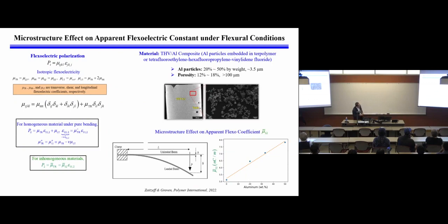Number two, we now know that for isotropic flexoelectric materials, the fourth order tensor looks very much like the linear elastic constitutive stiffness tensor, with two independent constants. Those two constants are the shear coefficient, involved in the gradient of the shear strain, like epsilon 12 or epsilon 21, for example, but the gradient, not just the strain itself. And the transverse means that if you have normal strain in the horizontal direction, then it's the gradient of that strain in the y direction, the perpendicular direction, that affects the output. So it only boils down to those two constants.